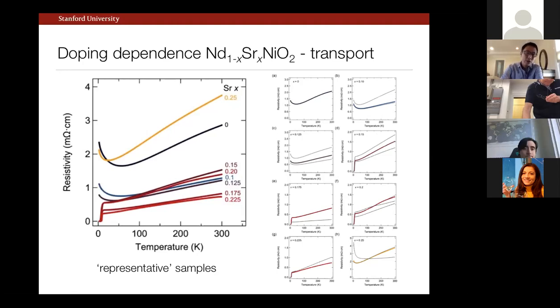But what's already strange, especially compared to the cuprates, is that the entire variation of the resistivity is rather narrow. It's within an order of magnitude or so. Right? And this is in strong contrast to the cuprates, where we have a good insulator for the parent compound, and what's known to be a pretty good, hopefully simple Fermi liquid metal for the highly overdoped non-superconducting samples. We have something rather peculiar with respect to those end members.